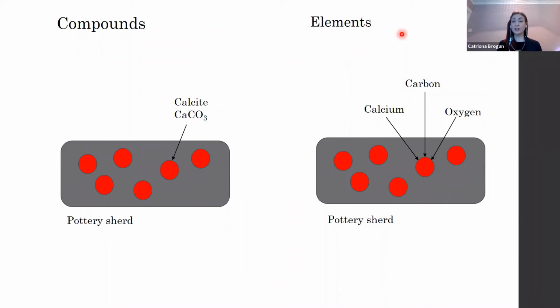And for example, you can look at the same sherd using 2 different techniques, and then depending on their output and what they are designed to analyze, they'll give you a slightly different story. So what we get with the first technique is pottery sherd will identify this red dot as calcite, and then we can use a different technique which analyzes the elements. So instead of calcite, it breaks it down into the various elements that calcite is made of, and it often gives you the relative amounts of these as well.